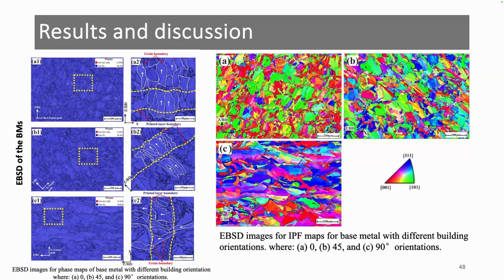While here in the 45 degree, we can see that the grain boundaries extend at an angle of 45. And here for the 0 degree, we can see that the extension of the grain boundary is in the same direction as the printing direction. And here, this is the IPF of the base metal. Maybe you can find that there is some preferred orientation for the 0 degree in 001 and 101, while in the 90 degree, there is some preferred orientation for 111 and 001. And for the 45, there are median orientations between the 0 and 90.